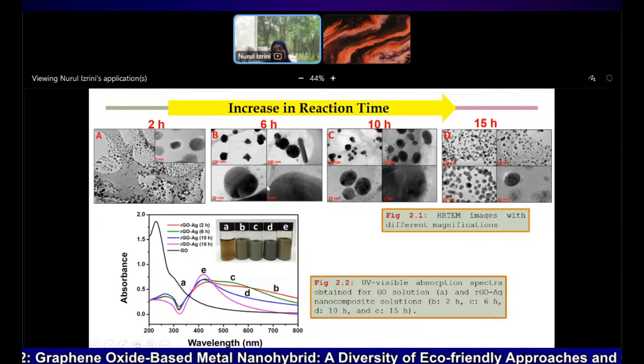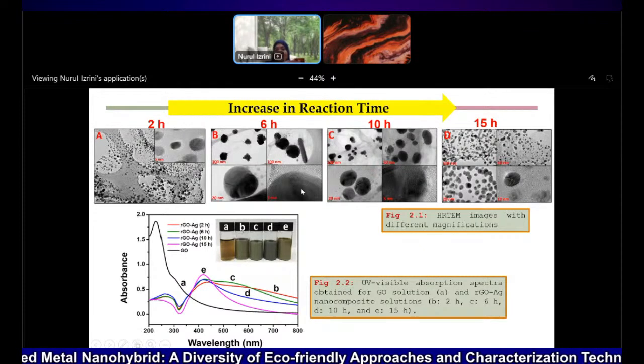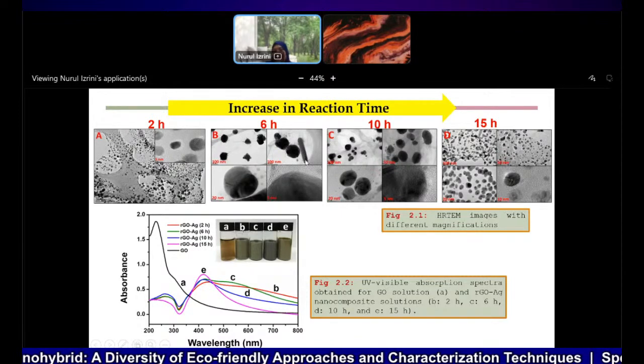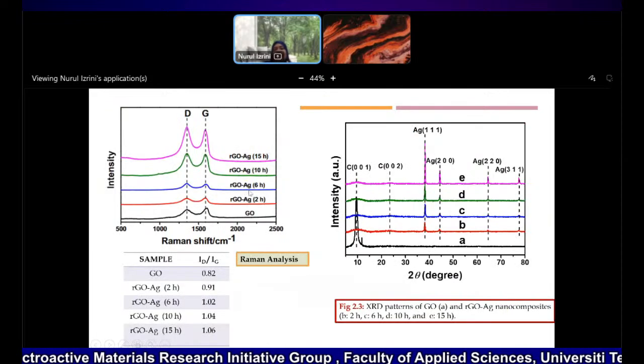So we also did HRTEM analysis because we wanted to know the particles formed after 2 hours, 6 hours, 10 hours, and 15 hours. We can see a large population of well-grown and spherical Ag nanoparticles after a reaction time of 15 hours. A sharp SPR band for the Ag nanoparticles reflected the formation of almost mono-dispersed spherical nanoparticles with an average size of 16 nanometers. Therefore, 15 hours is the suitable time to produce nanoparticles using glucose as a reducing agent.